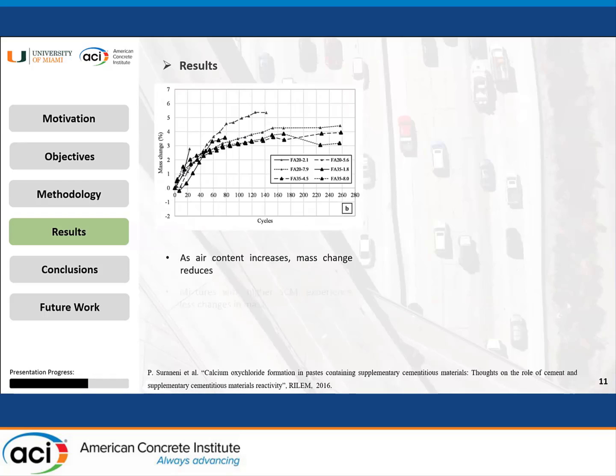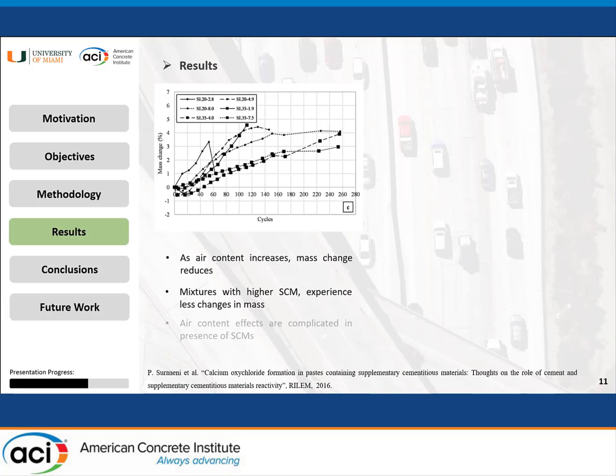Here we have the fly ash. So the mixtures with higher SCMs are experiencing less change in mass. And it's the same case for slag. We have the air content increasing, and it gets just more complicated when we have both air and the SCMs present in our mix design.